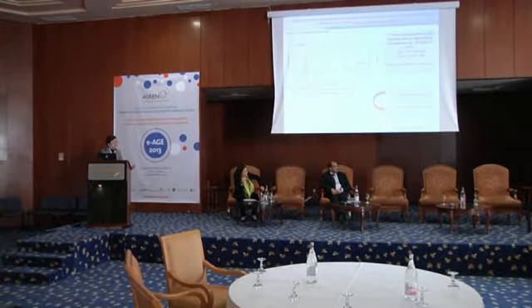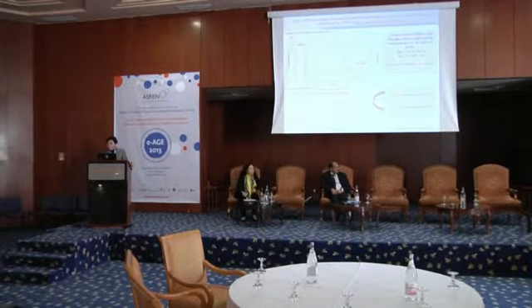our samples a high transmission coefficient in the visible range, and the intrinsic transition between the valence and the conduction band shifts a little when we vary the atomic % of dopant. We can see the fluorine-doped indium oxide thin films have a high optical transmittance, in the order of 80%. The optical band gap is 3.17 electron volts for undoped material, and it is in the order of 3.24 electron volts for material doped with fluorine. Then we can conclude that this material can be used as an optical window in photovoltaic devices.